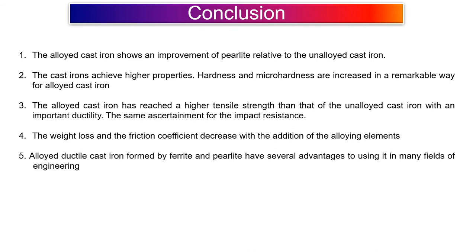Conclusion: The alloyed cast iron shows an improvement of pearlite content related to the un-alloyed cast iron. The cast iron achieves higher properties. Hardness and microhardness are increased in a remarkable way for the alloyed cast iron.